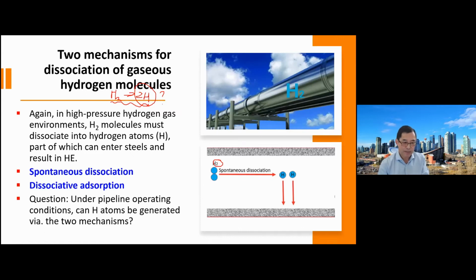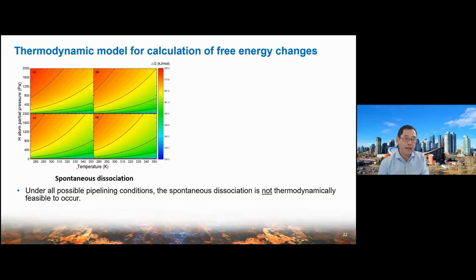That means H2 carried in the pipeline will, under the given condition, automatically decompose into H. That's spontaneous dissociation. The second one is dissociative adsorption. That means the H2 will diffuse towards the steel surface, and at the surface of the steel will decompose into H. That's the second mechanism. If you want to see whether hydrogen embrittlement is a problem, you need to critically evaluate whether the two mechanisms can happen under the pipeline conditions. Let's look at the spontaneous dissociation mechanism first. I don't want to go into too much detail. Based on the free energy change calculation, for spontaneous dissociation under all the possible pipelining conditions, this mechanism is not thermodynamically possible. So for hydrogen gas pipelines, you don't need to worry, spontaneous dissociation will never happen under the pipelining conditions.